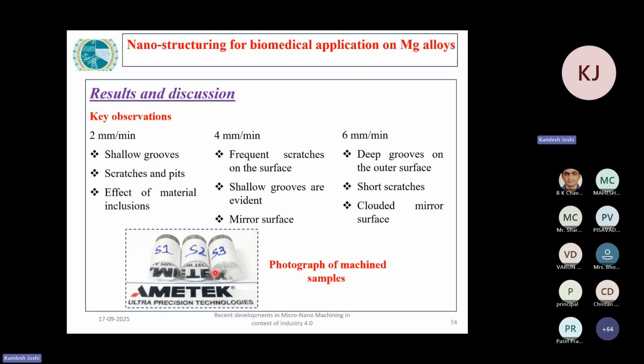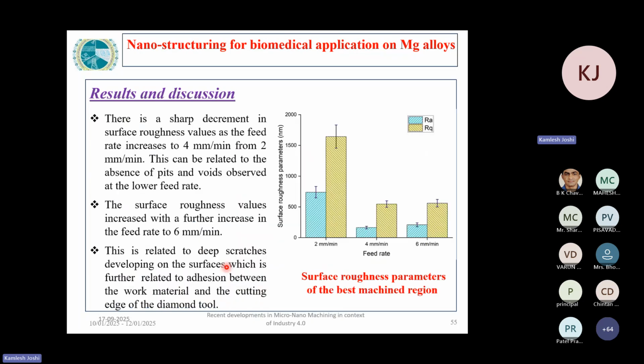So this is one of the photographs of the machined samples. If you see it directly, it looks like a mirror polished surface, but at the micro level it shows us the things which are happening in the material. So at 6 mm per minute, you can see the surface got some clouded type of appearance.